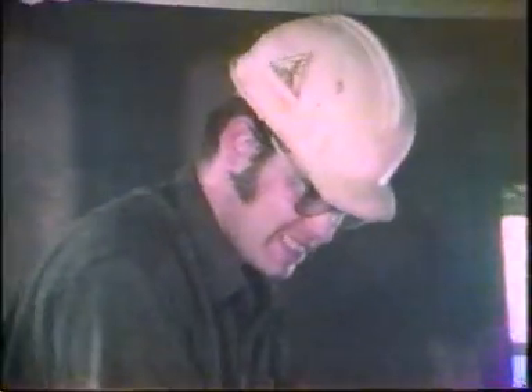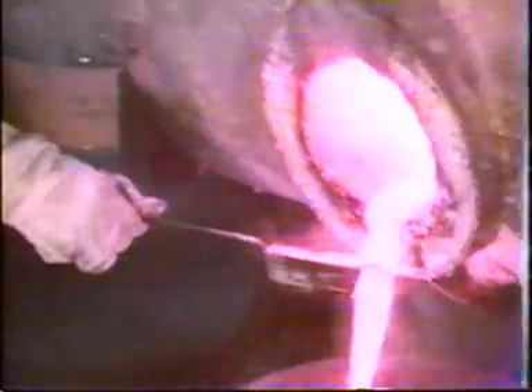The observer is carefully observing just how much he can take off before he begins to take too much gold. Small samples are taken in order to ensure that the slag is really slag and doesn't contain too much gold. But even so, the slag is itself used again in order to get every last piece of the precious metal out. Once most of the slag has been removed, the remaining, highly concentrated in gold, liquid is poured into molds. Most of the material which is spilling over here, in fact, is still slag. And what remains in the mold is mostly the gold.